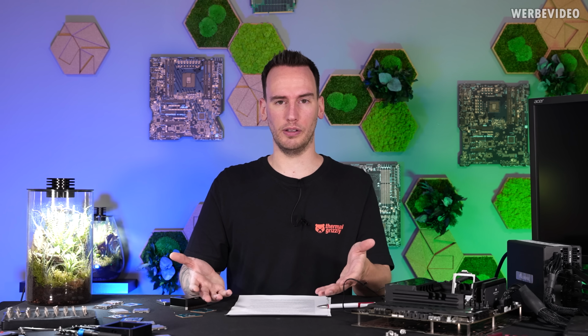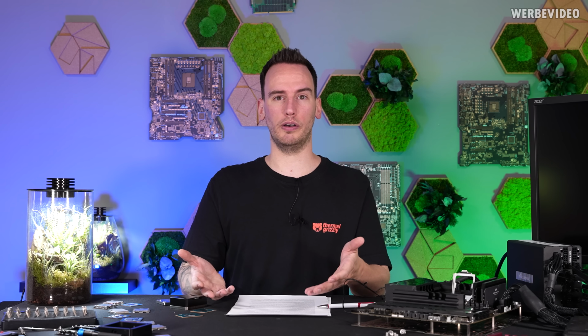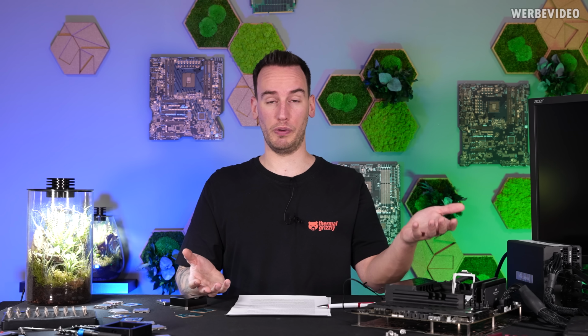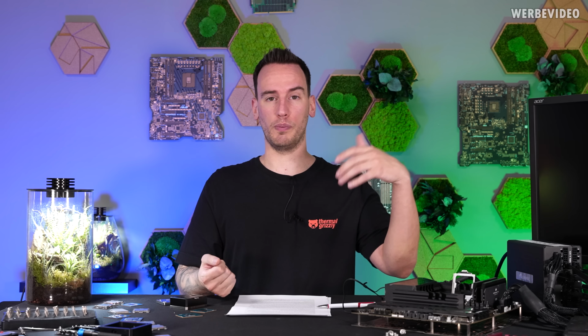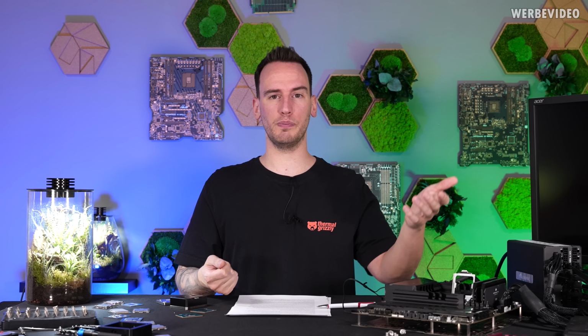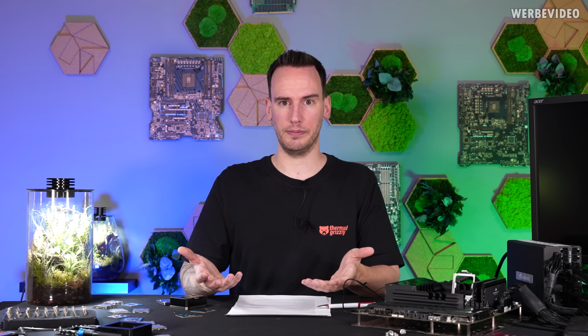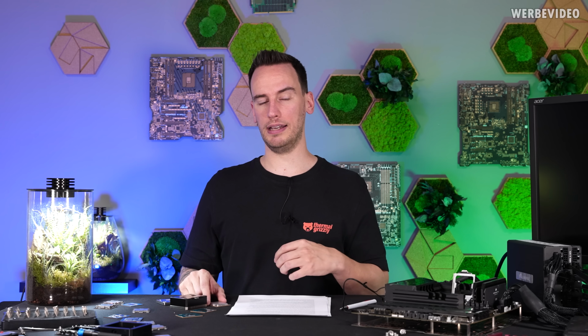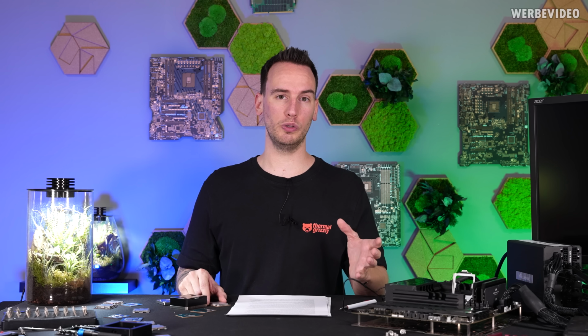It's like within tolerance. And I was like, yeah, that's what I assumed as well, but we see that it's not the case. We then also called our friends from Watercool and double-checked with them. They use a different copper supplier and a different nickel supplier, but they also confirmed to us they didn't see any kind of difference with nickel plating, but we did. The difference between TechN, Watercool and us is the application. We are doing direct die.